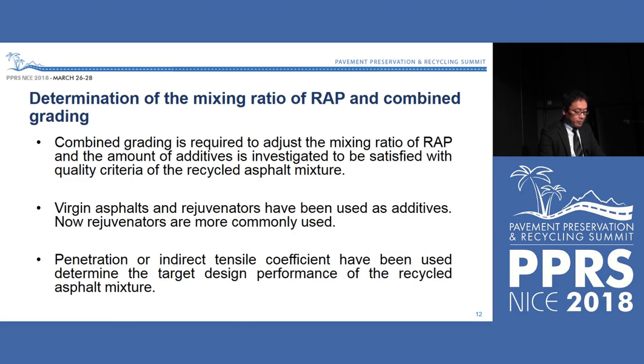Let me mention determining the mixing ratio of RAP and combined grading. Combined grading is required to adjust the mixing ratio of RAP, and the amount of additive is investigated to satisfy the quality criteria of the recycled asphalt mixture. Virgin asphalt and rejuvenators have been used as additives. Now rejuvenators are more commonly used. The penetration or the indirect tensile coefficients have been used to determine the target design performance of the recycled asphalt mixture.